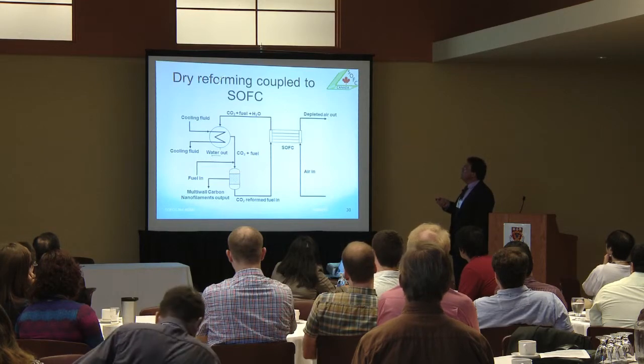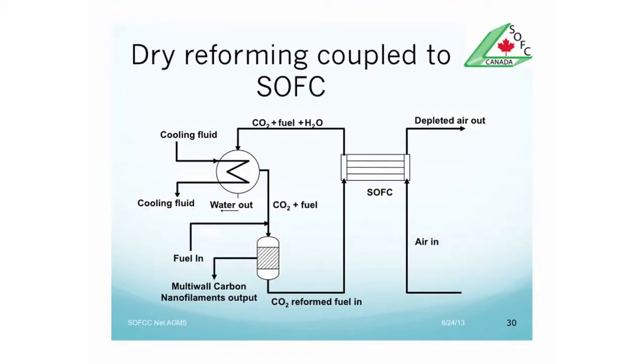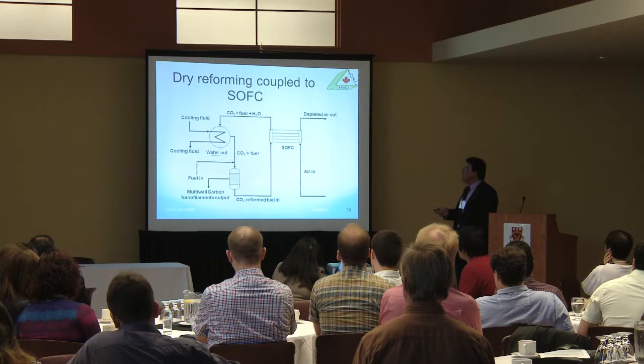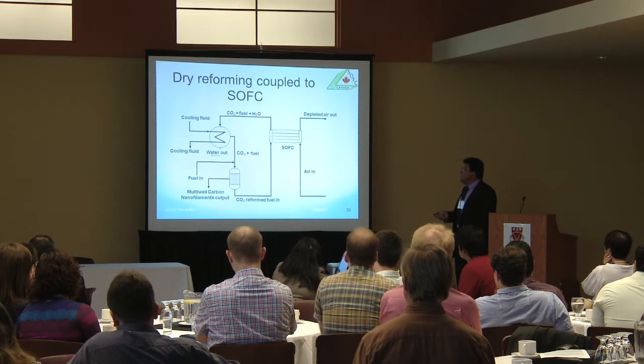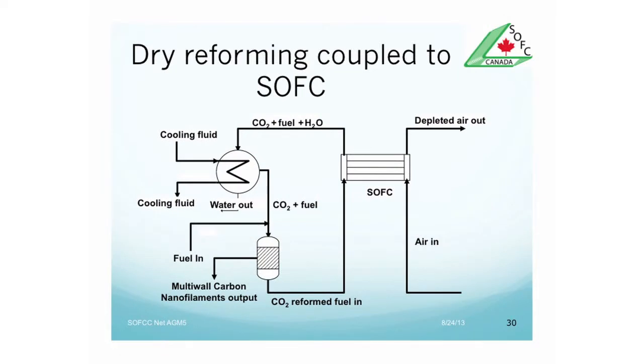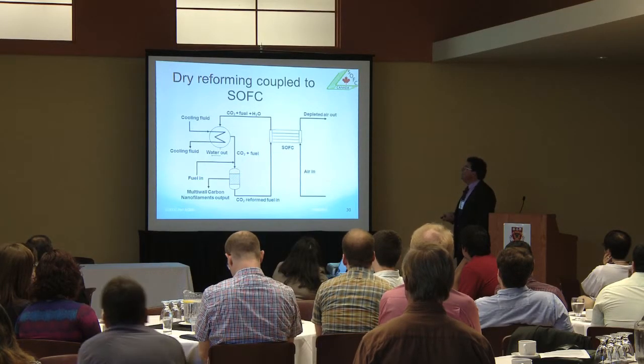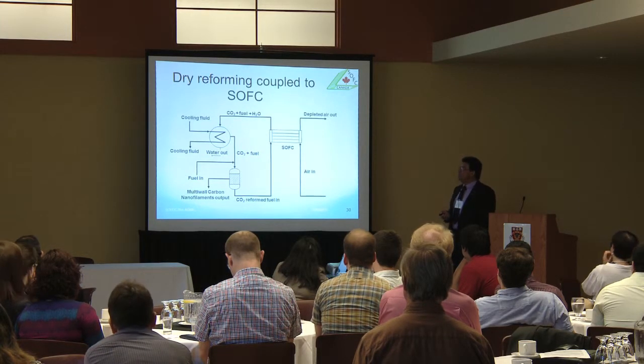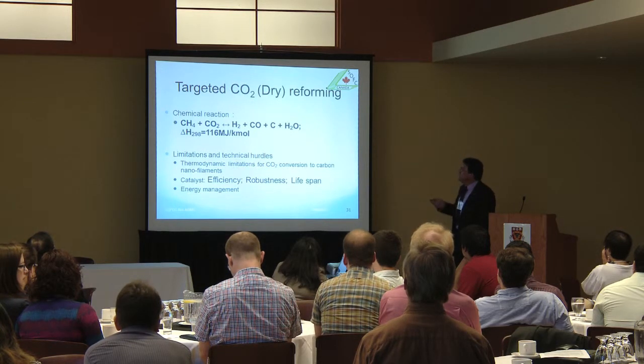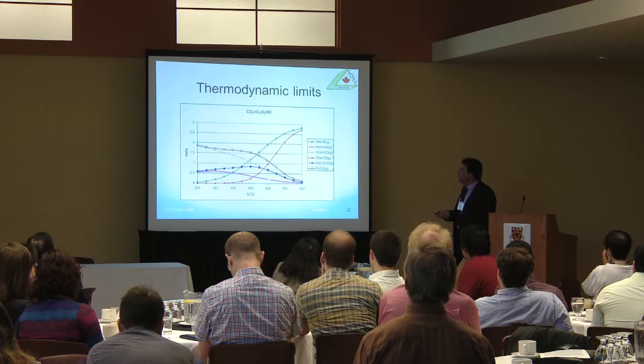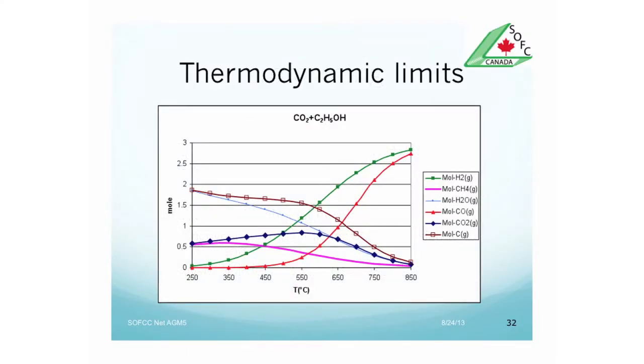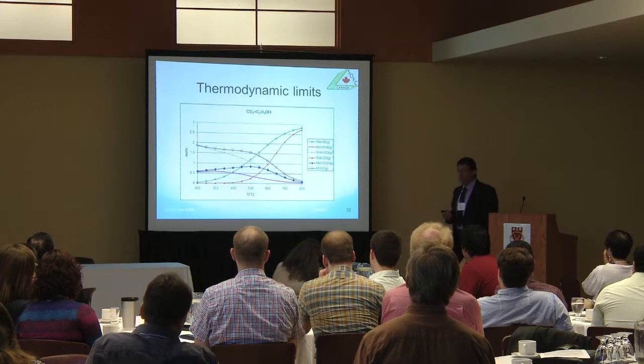If we couple this to an SOFC, we obtain this type of diagram. We have a fuel in the process, which is the reactor doing the dry reforming. This fuel is fed with CO2 and unreacted fuel, which comes from the outlet of an SOFC. At the outlet of this process, we get CO2 reformed fuel, which is feeding the SOFC to produce electricity, of course, by reacting with air. So, if we do the thermodynamics, we see that if we operate the reactor at 550, we can approximately get 50% of the carbon contained in the CO2 as a solid carbon which can be removed from the system.